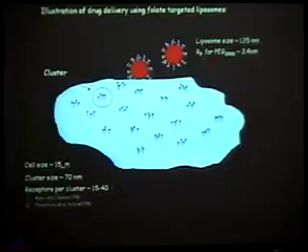Just to position you in size space with all these different species, liposomes that we work with are typically 100, 125 nanometers or so in diameter. The polyethylene glycol coating on the outside of these liposomes is a few nanometers, so that the Flory radius for a 2000 molecular weight polyethylene glycol molecule is on the order of 3.5 nanometers. Cells are 15 microns, so they're huge compared to the liposomes. So for all practical purposes, the cell surface can be considered flat.